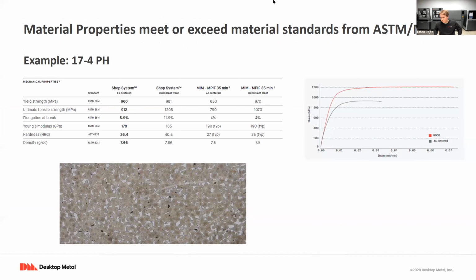So, our material properties really meet or exceed those standards that are set out by ASTM or MPIF standards. This is looking at a 17-4 stainless steel material where you're seeing a yield strength directly out of the furnace of over 650, 660 megapascals. Of course, the parts can still be heat treated if you want to. You get over 980 megapascals with that process. So you're still seeing these excellent material properties that you would need for these very, very industrial applications.